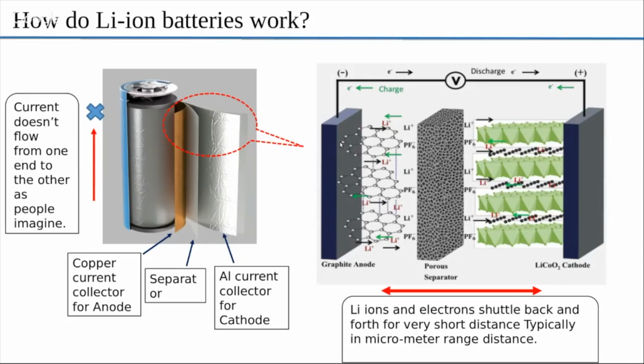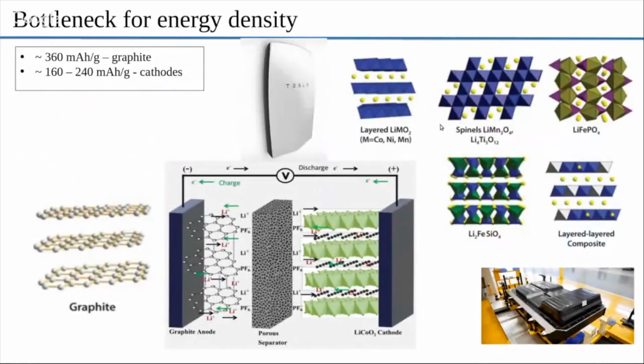So I guess we have given our viewers an idea of how a lithium ion battery functions, at least an overview. You have the anode on one side, the cathode on the other side, and the separator. Now, where is the bottleneck for energy density? Everybody wants longer range, lighter, long-lasting batteries, but there is a bottleneck. There has to be. That's a challenge right now, which is the energy density. The energy density problem can be traced to one material more specifically. On one side, the graphite anode has a 360 milliamp hour per gram capacity. And for the cathode, for example, the Powerwall uses lithium NCM, lithium nickel cobalt manganese. That has a layered chemistry, and spinel oxides are used in the Nissan Leaf. The BYD buses and trucks use lithium iron phosphate.